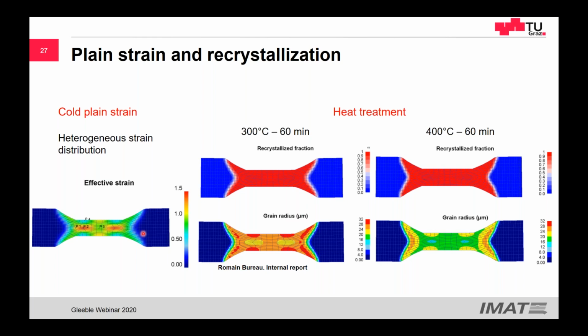But this is everything cold. Then when we increase the temperature, we do it in a furnace, so there is also no temperature distribution here. What we have is a heterogeneous recrystallization grade, not visible here because it's over time, and also grain size variation due to the stored energy, so due to the deformation here. If we deform more, we get finer grains. So there is no temperature gradient in this specific slide. There's only a strain gradient due to friction and grain size distribution due to different local strains. Okay, great.